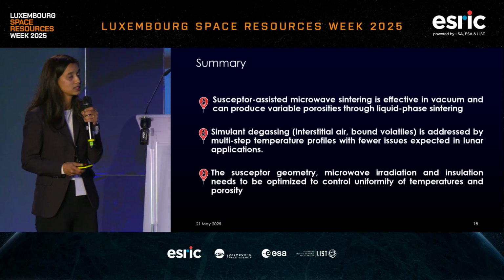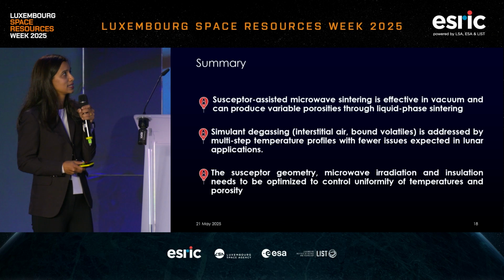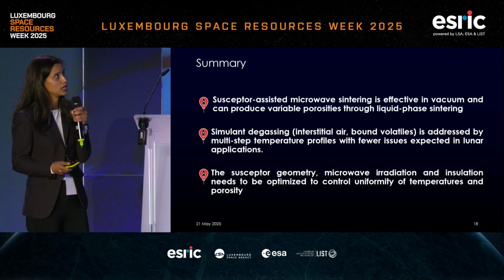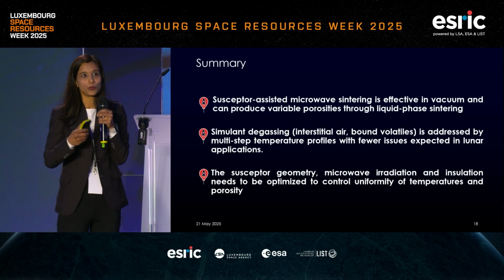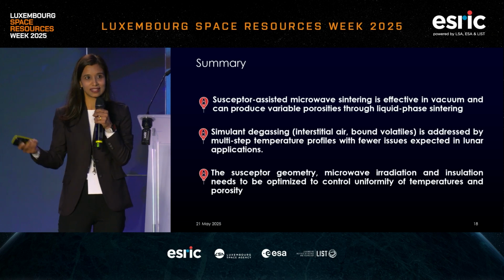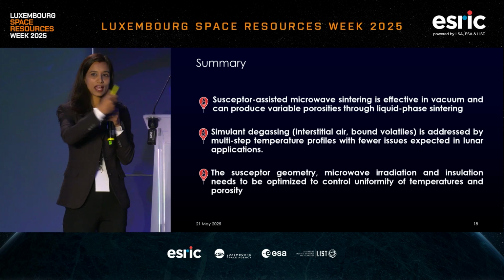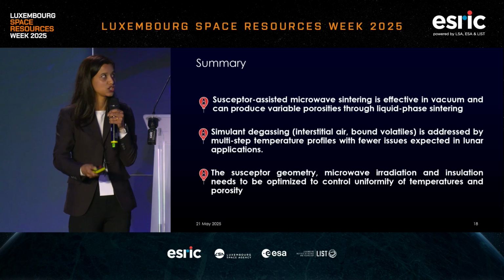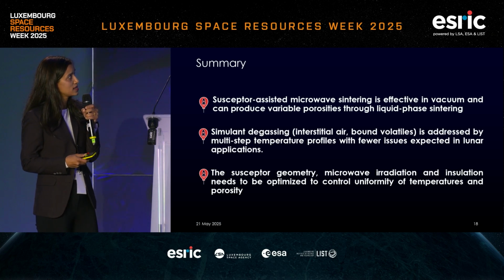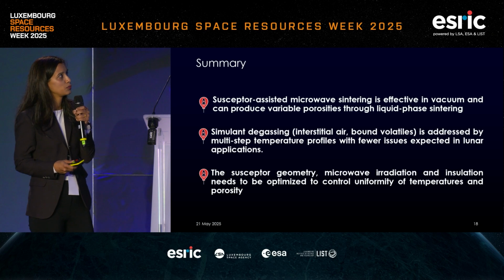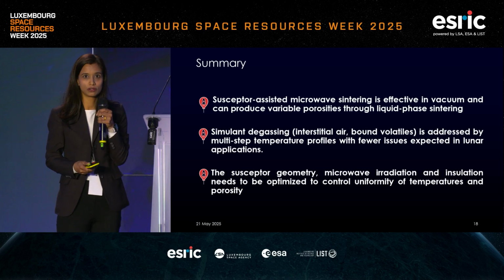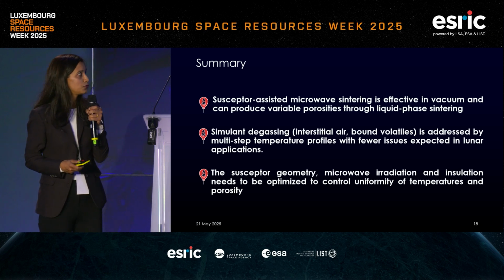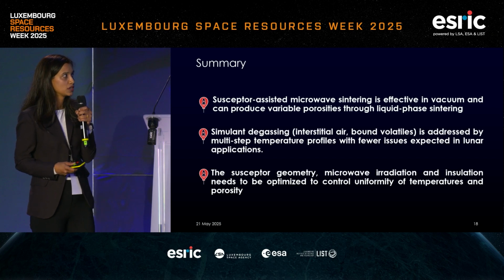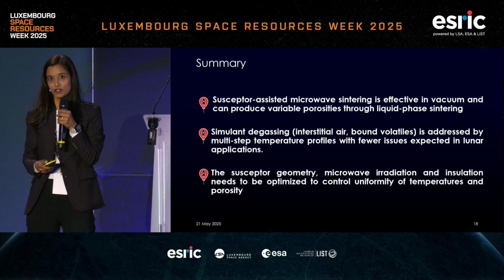Susceptor-assisted microwave sintering is certainly effective in vacuum, and it can produce variable porosities through liquid phase sintering. So we are able to achieve samples of different porosity, which goes back to what we are trying to achieve for different applications. We could also address the simulant degassing by multi-step temperature profiles, and we expect fewer issues in lunar conditions. And now the focus is on optimizing the susceptor geometry, the microwave irradiation, and thermal insulation to control the uniformity of temperature and the porosity and hardness of the final product.